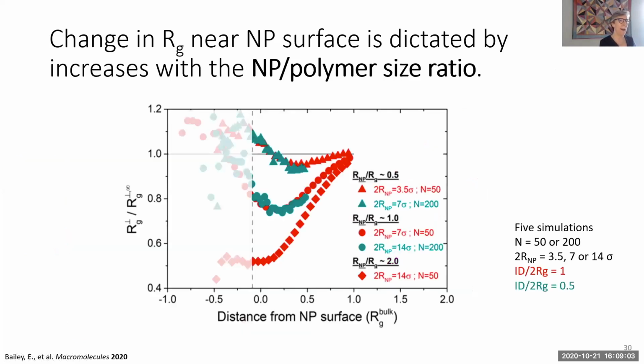The one thing I do want to highlight, and this is a little bit of a pet peeve I have with nanocomposite studies, is that I really think the important parameter when you talk about chain conformation is not the particle size. It's not really the interparticle distance, unless it gets very small. And it's not the polymer size. What's important is the nanoparticle to polymer ratio. Right? The extent to which a polymer is distorted by the particle depends on both the particle size and the polymer size. And that's clearly represented here, where the red data is the smaller chain, the green data is the bigger chain, but the symbols tell you what the ratio is. And so both triangle sets sit here, both circles sit here, right? So we need to think about that ratio when we think about the distortion of the chain conformation.